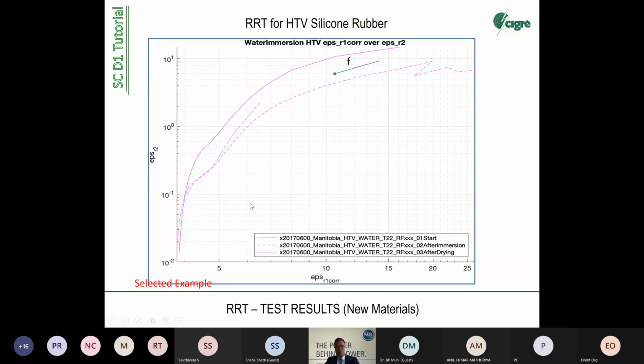And this was done here after different stages of water immersion. So start, after immersion, and after drying. And the tendency was clearly with the frequency. So you moving down into the lower losses and lower permittivities. Also, absolute values, they cannot be correct here. As you can see, it's not the absolute values that you get from the measurement of a standardized method.